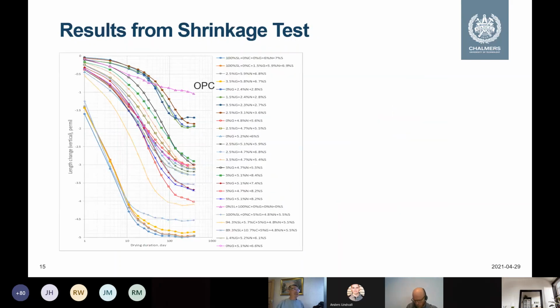So this is shrinkage. You can see that this is ordinary Portland cement shrinkage. Here I compare only with the mortar. So I think the concrete has a similar tendency. From the mortar, you can see that ordinary Portland cement after 1 year is around 1 per mil, 0.1%. Then for pure alkali-activated slag, it is about 5. You see here, 5 per mil.